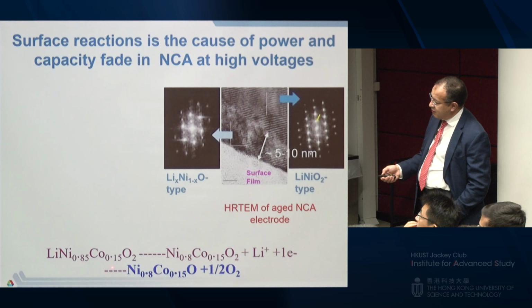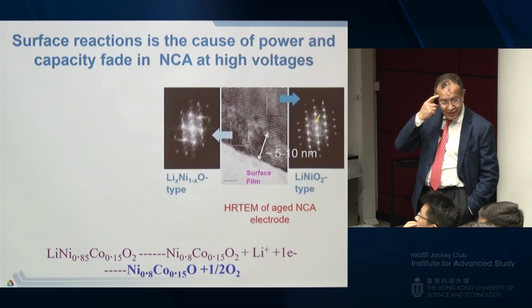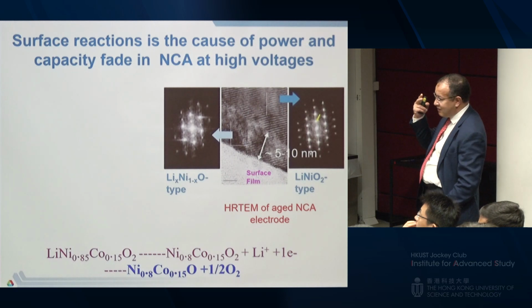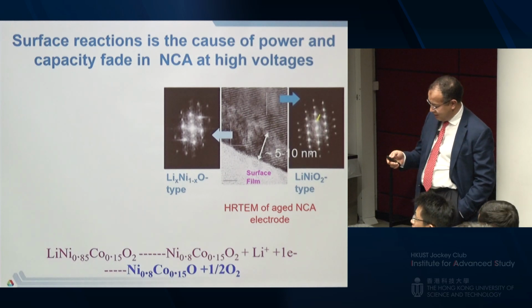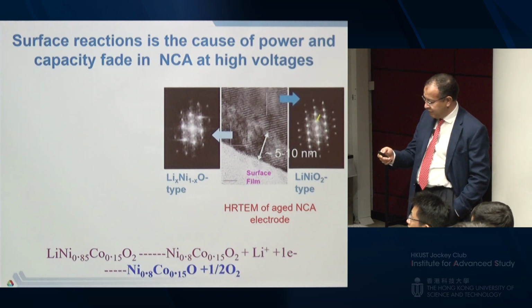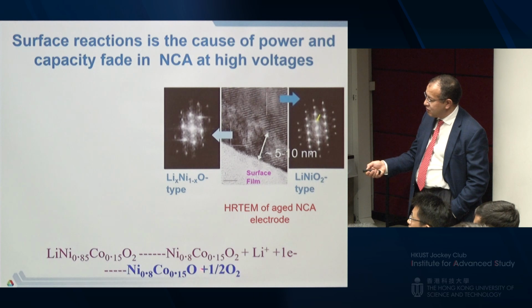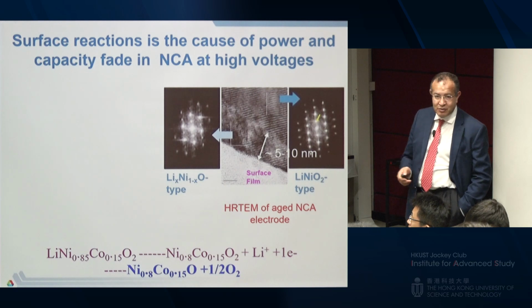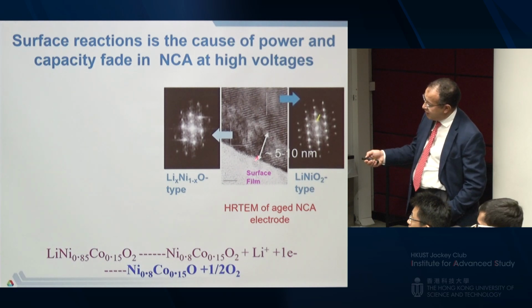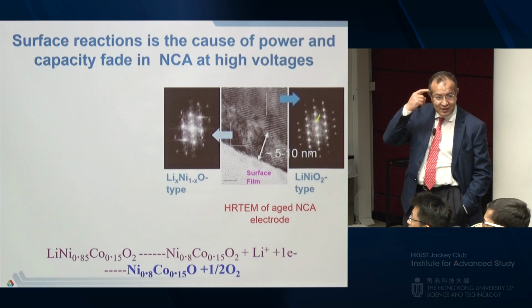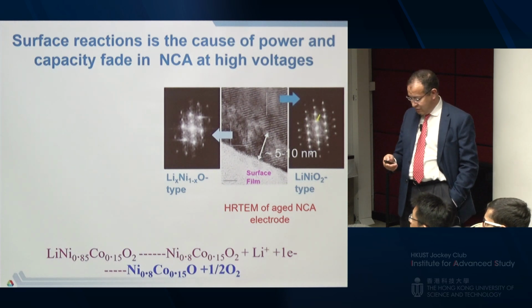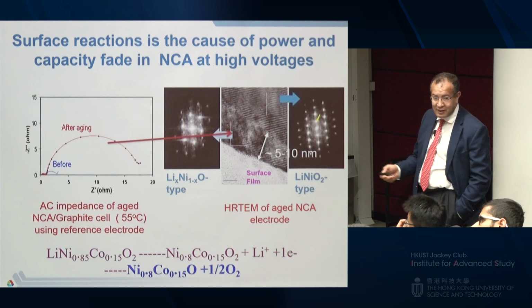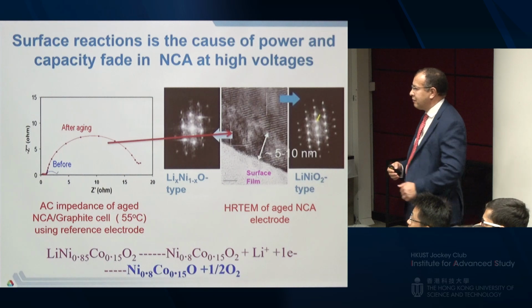So what happens is, when you take this material and remove lithium at high voltage, you create this phase, which is thermodynamically unstable. Nickel 4+ doesn't exist in an oxide phase. Manganese oxide is 4+, but nickel always reduces immediately and generates oxygen. So this phase here is nickel oxide, that's what you see here, and the oxygen reacts with the electrolyte and gives you a surface film. Now we have a very large SEI where lithium has to struggle to go through it during charge and discharge. As a result, you lose capacity because your interfacial impedance grows significantly. That's how you lose the cycle life.